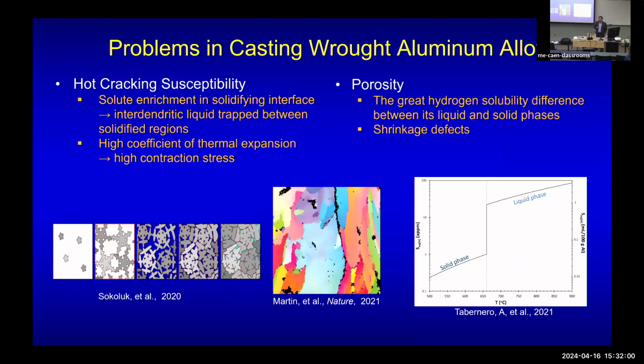So here, why are wrought alloys, aluminum alloys, difficult for casting? Its number one killer is hot cracking susceptibility. It's because during solidification, like we mentioned, the traditional methodology is you have dendritic growth, right? They quickly occupy space, and then they encircle the liquid in the solid phase. The liquid has no way of backfeeding, no way to compensate for the shrinkage depth. Then they have hot cracking there. Like a lot of hot cracking, or you have huge grain growth there.